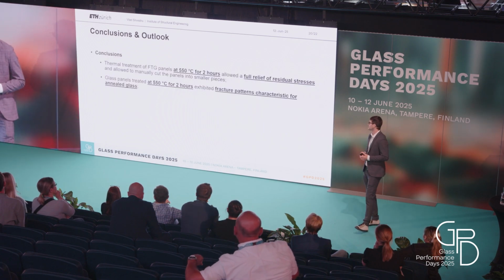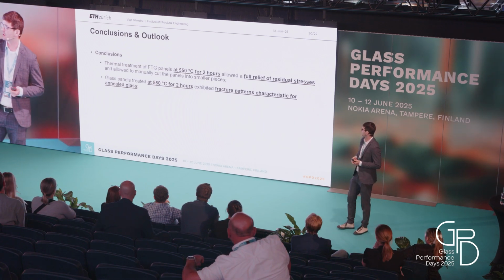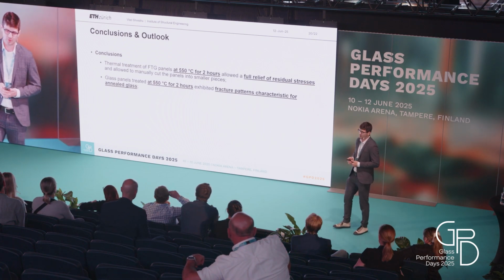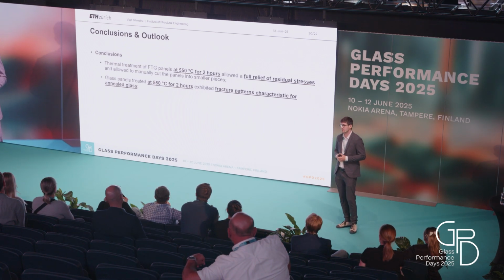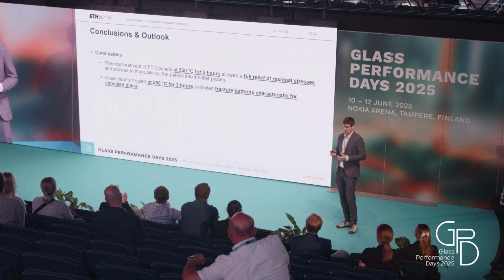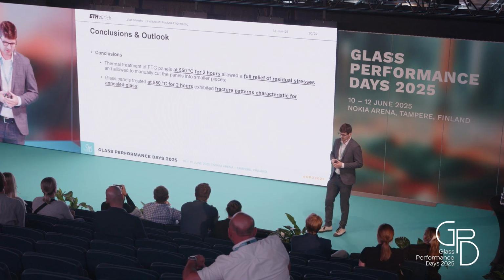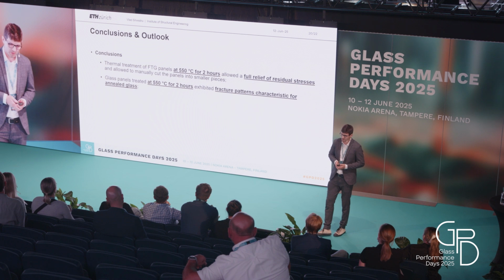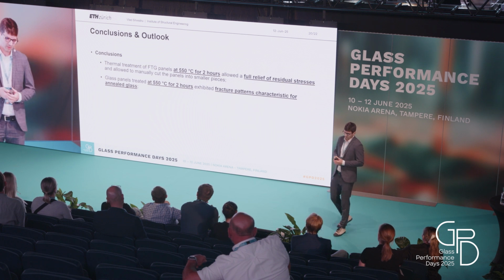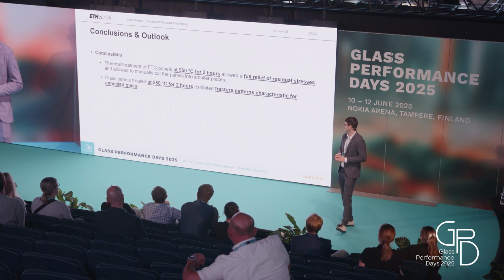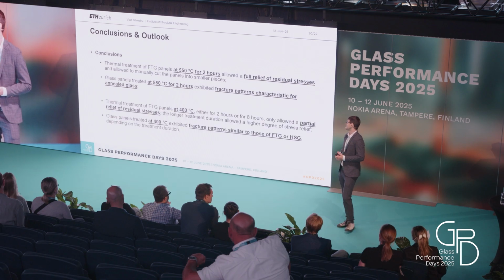I come to my conclusions. Thermal treatment at 550 degrees for 2 hours allows a full relief of the stresses. It also allows to cut the panels to whatever sizes are needed afterwards. Also, the fracture pattern is characteristic of annealed glass afterwards.